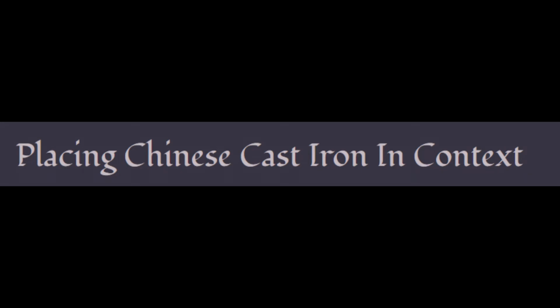Why? Well, the key thing to note here seems to be that the malleabilization or fining process was long and fuel-intensive. As opposed to the bloomery processes, I don't know as much experimentation with this, but I have seen fining times quoted in the range of several days to properly turn cast iron into steel or wrought iron, time during which the iron must be kept open to the air, so it is cooling on its own, and also at least nearly molten. Indeed, the one method to keep the carbon content relatively uniform was to keep the iron completely molten and to stir it regularly as it decarburized, which might also have shortened the time required. The fuel demands of that method would have been enormous.